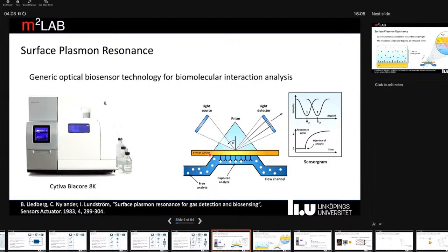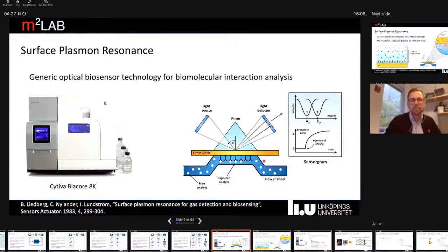which essentially is an optical technique which uses the properties of propagating surface plasmon at the metal dielectric interface, such as this gold surface that we see here. And then we can turn this into a biosensor by immobilizing biomolecules on the metal, interfacing the medium around the metal, and then detect ligand-analyte interaction as it occurs on the surface. And essentially what we monitor are changes in reflectivity as we change the refractive index in the vicinity of this surface. So a shift in the reflectivity of light irradiated at the surface. And we can do this detection in real time. So look at analyte ligand interaction as it happens on the surface.